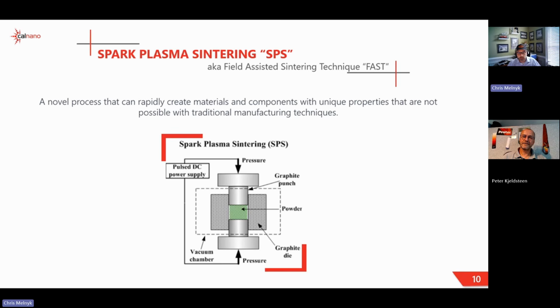And so then we were putting all this time and effort into making these nano-grain materials, and then destroying them somewhat by applying too much time and temperature through the hot isostatic pressing. So it became micro and not nano. Exactly. And so then we said, well, what's the best way to keep nano grains nano and consolidate these things? And that's what led us to SPS. And so we were one of the first commercial adopters in our area at the time.